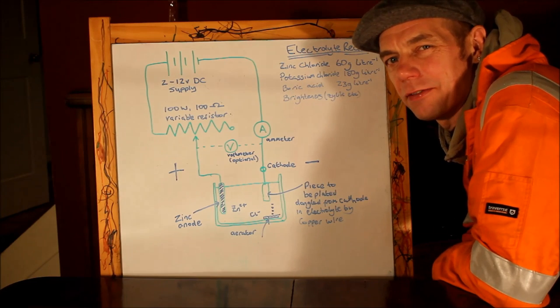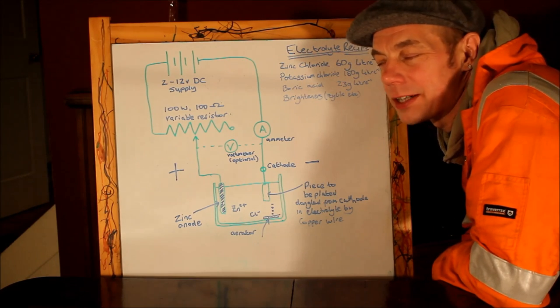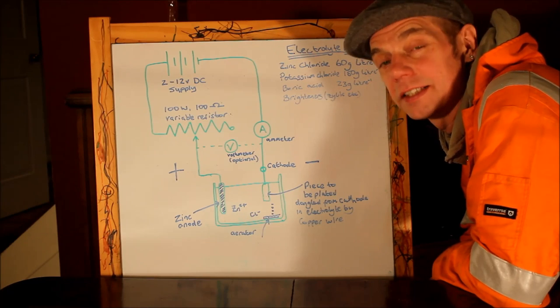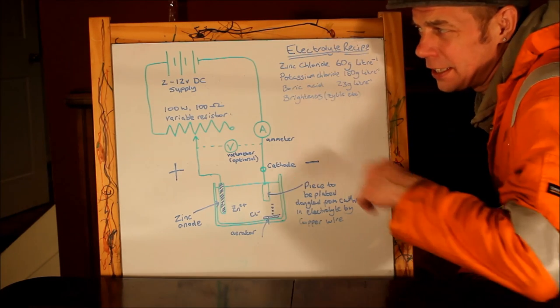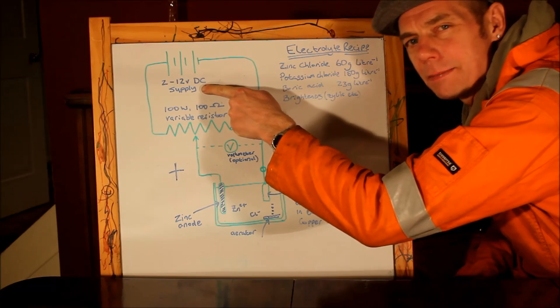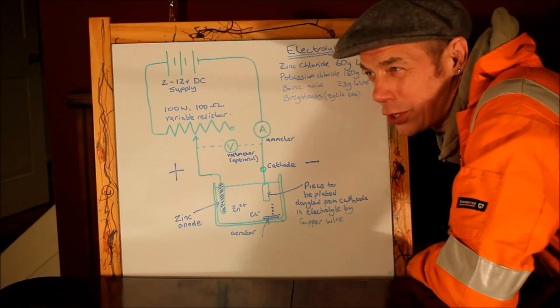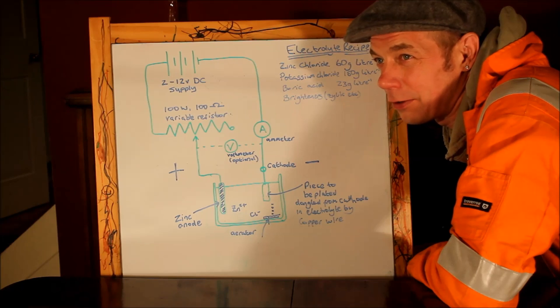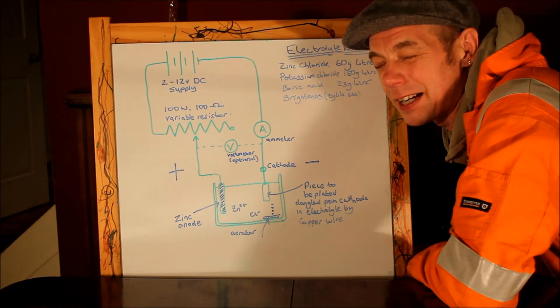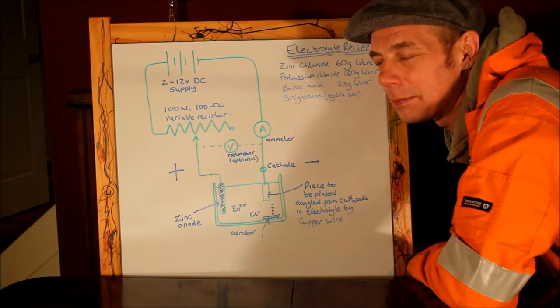Cleaning's important, but it's not very interesting. Now the exciting part, we're actually going to do the plating. So here's what you need to set up for your plating tank. The first thing you need is a DC power supply between about 2 and 12 volts. The ideal voltage is probably around about 6 volts, but actually the voltage isn't particularly important.